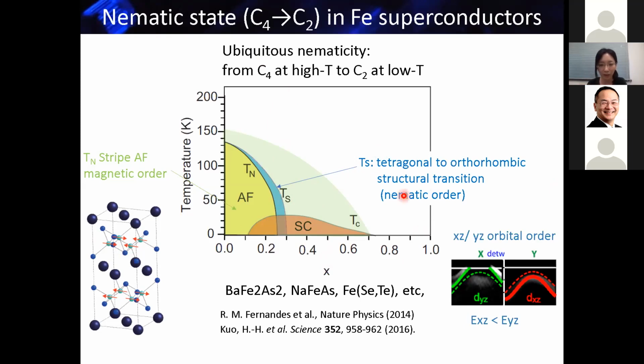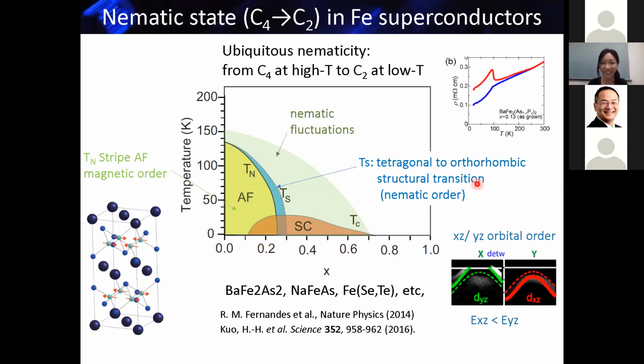Of course, these are very coupled to each other, but there is also an XZ and YZ orbital order. In the four-fold symmetric case, YZ and XZ should be completely degenerate. But when you cool this system down below this temperature, the energy levels of XZ and YZ become non-equivalent. That's what we call the orbital order. In the iron-based superconductors, many things happen, and at low temperatures the system becomes two-fold symmetric. Also at high temperatures, fluctuations of these two-fold symmetric signatures remain, sometimes called nematic fluctuations, and they appear in the anisotropic resistivity.